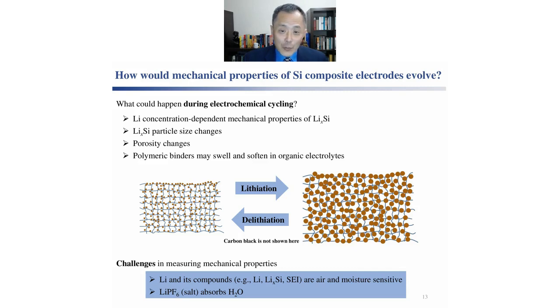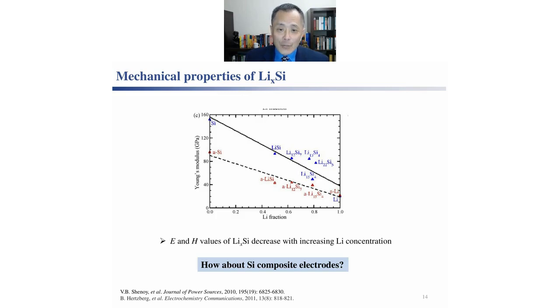The mechanical property measurement of electrodes can have several challenges. For example, all these materials are air and moisture sensitive, and we have to avoid their influence. We therefore have to perform mechanical property measurement in an inert environment. There have been some studies, both from density functional theory calculations and mechanical property measurement, showing that for silicon lithium alloys, the Young's modulus decreases with increasing concentration of lithium in silicon. This is not surprising because silicon is covalently bonded, whereas lithium is a very soft, low melting point metal. As we put more lithium into silicon, modulus is expected to decrease. The question then is, what is the mechanical behavior of the composite?